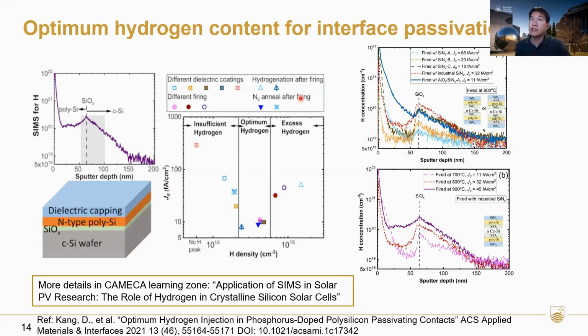So the higher it is, the worse it is. We see that there's an optimal trend, a trend that shows an optimum in the middle here. If there's not enough hydrogen, there's not enough passivation of the dangling bonds. If there's too much hydrogen, hydrogen itself starts to become a recombination center and starts to become a problem. If you're interested, you can find out more about it. I think it's still on the Kameka Learning Zone, one of the webinars delivered by my colleague Di Kang.